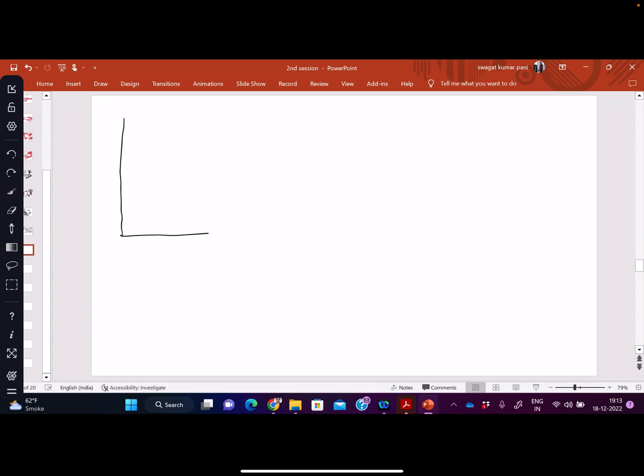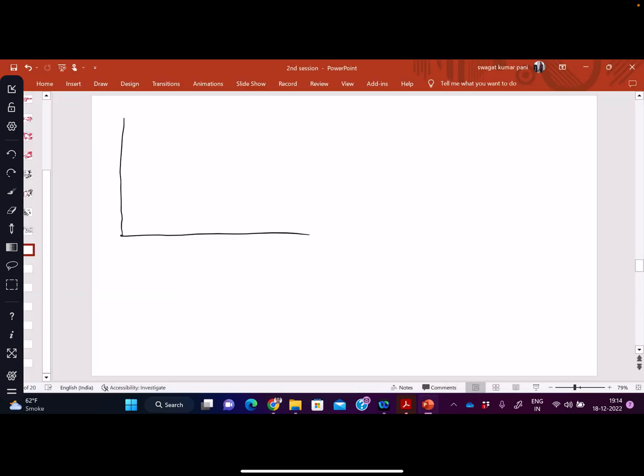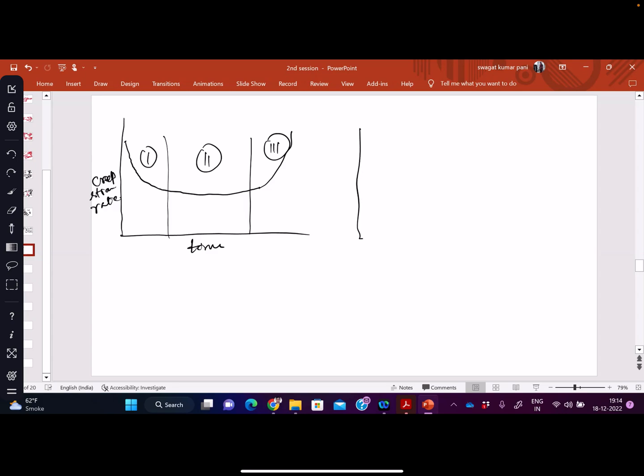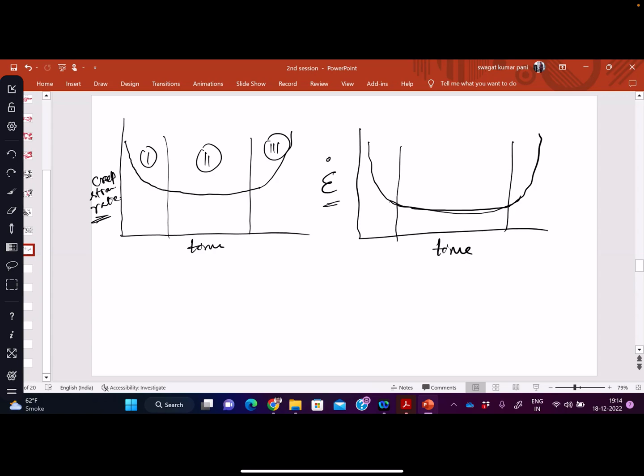So that was strain versus time. If we plot strain rate versus time, suppose we plot creep strain rate versus time, we get a curve. First there is decreasing strain rate like this, then it will go something like constant, then it will again increase. So here it is region 1, region 2 and region 3. Similarly, if we plot creep strain rate versus time, we get this kind of curve again. It will be almost constant and then these three regions.